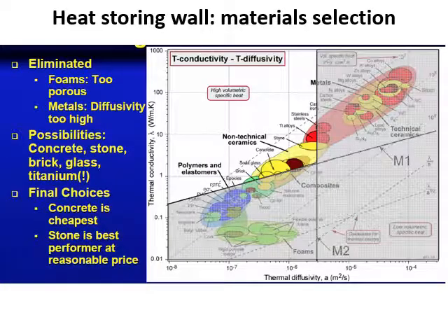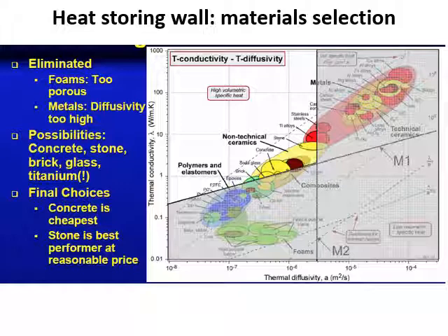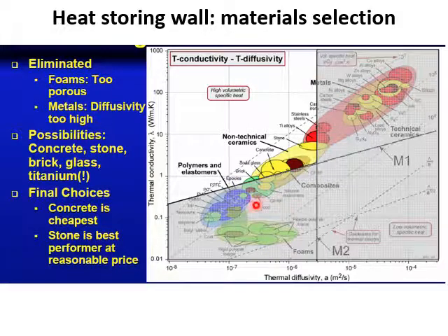Okay, here is the material property chart having thermal conductivity versus thermal diffusivity. So using these two material indices M1 and M2, M2 is already fixed, which is 3 times 10 to the negative 6 meter square per second. So you should draw a straight line over here, and the value needs to be lesser than that. So everything bigger than this value should be neglected. And then the second material index, which is the line over here. Okay, so thermal conductivity divided by thermal diffusivity. So above the line would be the shortlisted material.